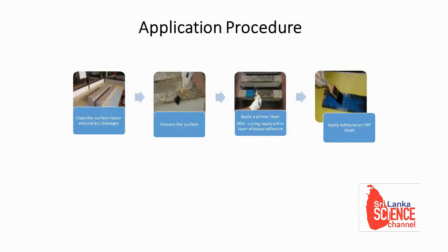The application procedure is very simple, and all the guidelines are well documented in construction manuals. Normally we have to prepare the surface. That means if we have any defects such as cracks or damages, first we have to repair them and make the surface clean. Then we have to expose coarse aggregate to have enough roughness for the surface to be bonded. We can use either sandblasting or water jet. Then a thin layer of primer has to be applied on top of the surface. That's only for improving surface energy for proper bonding.